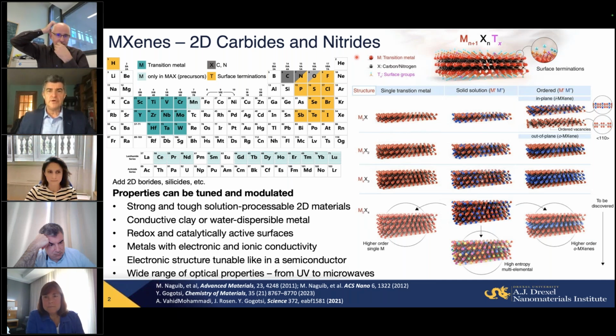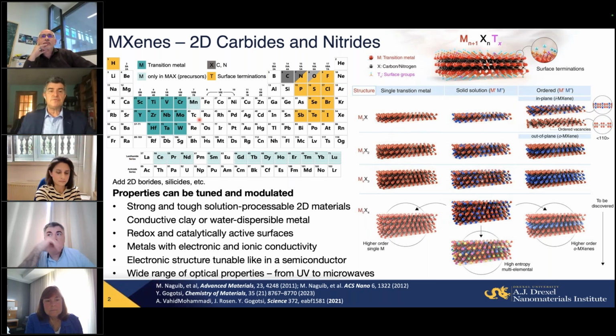And as you have already heard from Kostya, there are many 2D materials available. You have heard about graphene, dichalcogenides. In 2011, with my colleagues and students at Drexel, we discovered 2D carbides and nitrides, MXenes, where M stands for a transition metal, X carbon and nitrogen, T means surface terminations. You can build them out of a dozen transition metals. Lanthanides can substitute for one of them. Carbon, nitrogen connect metal atoms in these layers, and the surface can be oxygen, hydroxyl, amino groups, chalcogens, halogens, phosphorus,